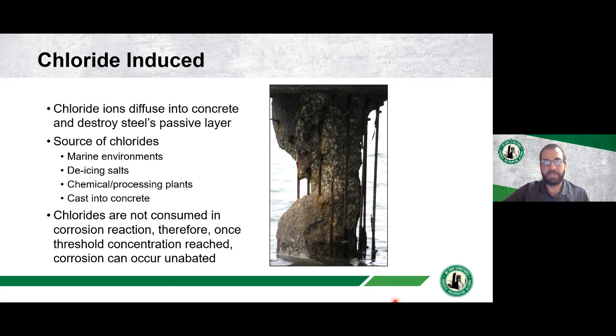So obviously a source of corrosion is chloride induced corrosion. Chloride ions penetrate into the concrete, destroy the steel's natural passivity, and cause corrosion. Typically these chlorides can come from marine environments, de-icing salts, and chemical processes. Sometimes they can get cast into the concrete. So once the chlorides reach the steel and break that passivity, there's no going back. They're not consumed in the reaction. So once they break the passivity and allow corrosion to occur, then corrosion can occur unabated.